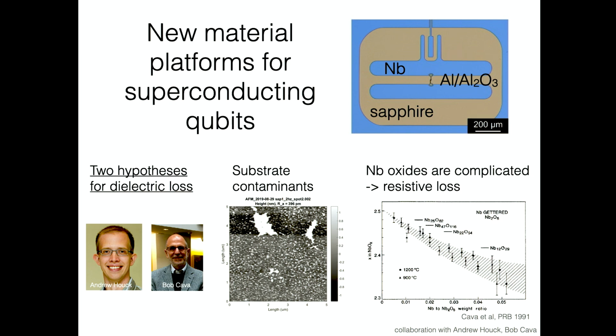And we said, Andrew, what is the material system that you guys are actually using, and what do you know about it? So the Houck lab qubits at the time were mostly made out of niobium. They have an aluminum oxide junction to form the Josephson junction in the middle. And then the whole thing is sitting on sapphire. This is essentially the IBM material stack too, but they work on silicon instead. And we immediately came up with two hypotheses for where this loss might be coming from.